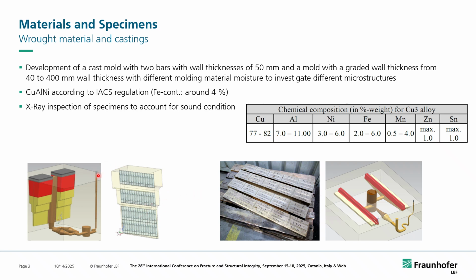On the other side, we wanted to investigate a bit the wall thickness influence. So we had a casting block with a graded or a step-like design, starting from 40 millimeters up to 400 millimeters. At the end, this will lead us, this was our hope, to different microstructures and to fewer defects in the lower part, the 40 millimeters. And since this is cast upright, we have a lot of casting pressure from the material in the melt that is putting a lot of pressure on those lower wall thicknesses here.